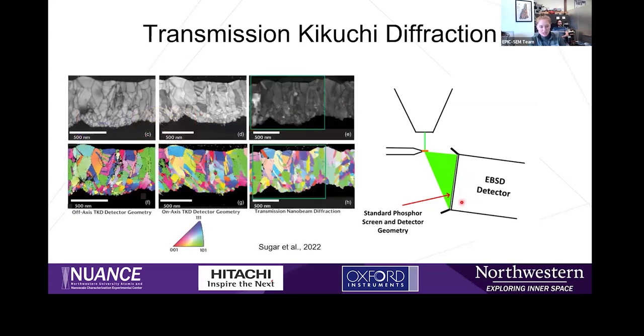This is a paper from 2020, I put 2022, but Sugar et al. in 2020, where they compared off-axis TKD, on-axis TKD, and nanobeam diffraction in the TEM. What you can see is that they're actually pretty similar. You can get similar results in the SEM using TKD. On-axis geometries are a little bit better. You get a little bit more detail. In the nanobeam diffraction, you get more precise angular resolution, but the process of doing all of this in the TEM is a lot slower and more complex. So if you don't need that kind of resolution and you want to just do it all in the SEM, doing transmission Kikuchi diffraction could be very useful.